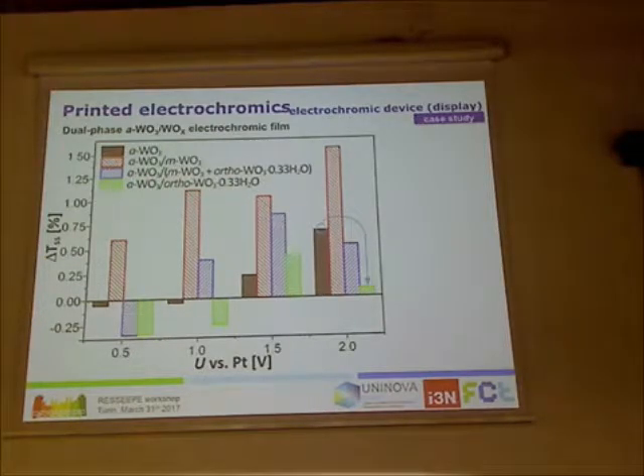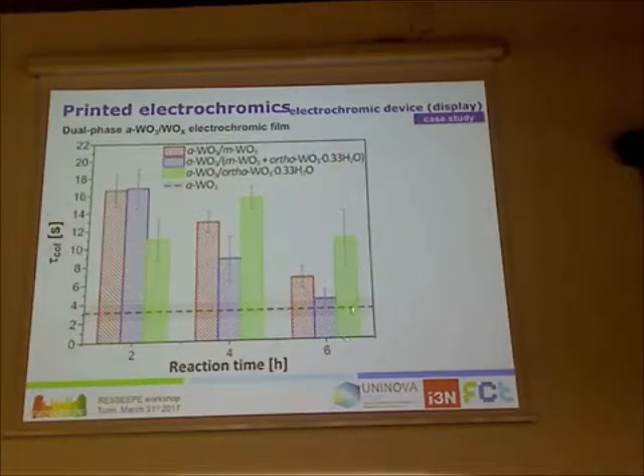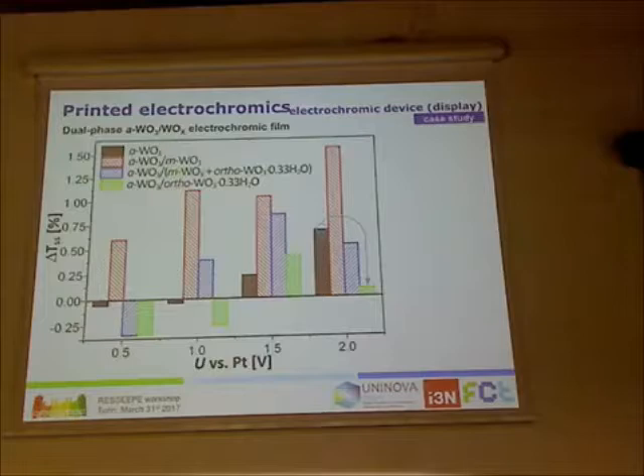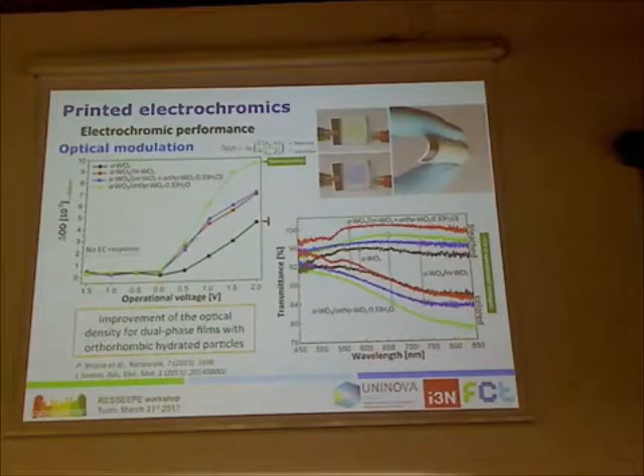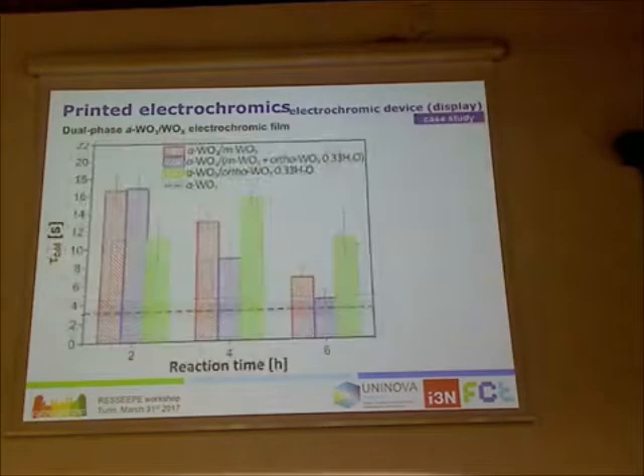For this dual layer mixture, without compromising too much the switching time, because it also has to do with the total area available, if you compare for instance with an amorphous layer that has the fastest switching time. But nevertheless, the most important point is that for the same voltage you can improve the optical density.